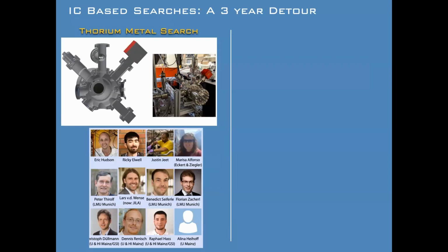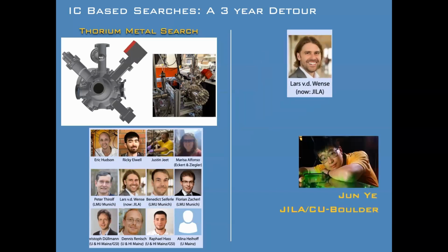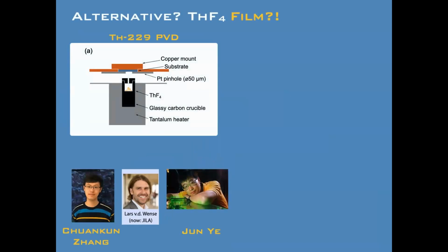So we were very fortunate that we had been doing this thorium metal search that I mentioned earlier. What we were doing here was coating thorium, other people were doing it. We were coating thorium onto substrates, like thorium oxide at the time. And then that's what we were using as our target. So Lars von der Wense, who was in Peter's group, went and did a postdoc with Jun Ye. And Lars said they were also working on this with us, that these samples that we're getting, they're just never going to work. They're not good enough. We need to learn to make our own samples. And so he built up in Jun Ye's lab at JILA this physical vapor deposition system that could deposit a super radioactive thorium on the substrates. And so once we had found a nuclear transition, we talked to these guys.